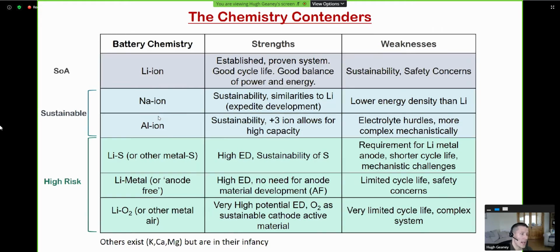If we then move on to what we class as high-risk systems, these are probably further out again, although there has been some very good progress made in terms of lithium-sulfur batteries. With lithium-sulfur, we can potentially get a higher energy density, and we also have the benefit of the sustainability of sulfur as a cathode material. One of the issues, though, is the requirement for a lithium metal anode. And we also, in general, have a shorter cycle life compared to lithium-ion batteries. And we have quite a complex mechanism in terms of how it operates, so we have major mechanistic challenges that we need to overcome.